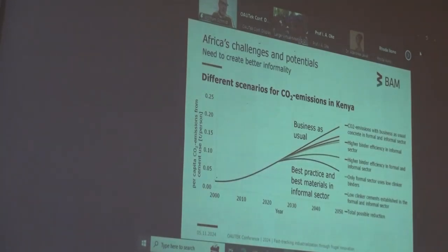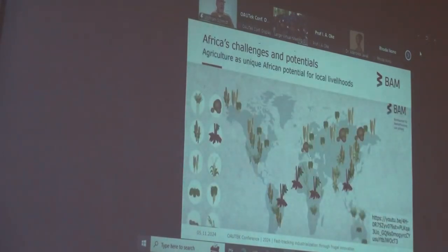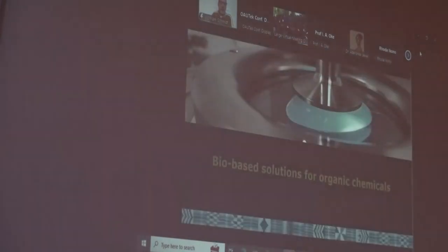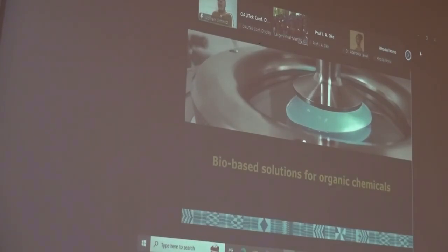Like here, you can see a prediction until the year 2050 for Kenya, how per capita CO2 emissions could be developing if we would have a change in mindset, if we would use the best possible binders and we would use the best possible practices, including the informal sector. Then the projected CO2 emissions by 2050 from here could be going down as low as here. We could even turn the trend and get lower with our carbon emissions in the future, if that would all be applied. And the potentials to get there in Africa are particularly bio-based materials. So I would like to introduce you to a few bio-based resources that could become potentially interesting for high-performance concrete.